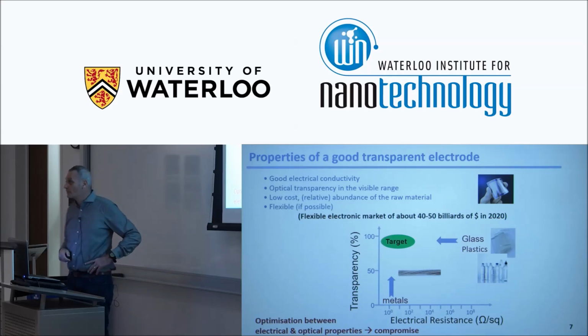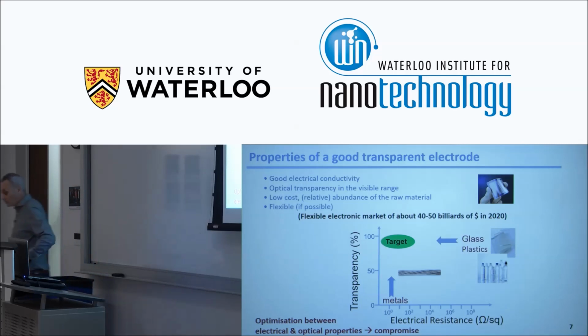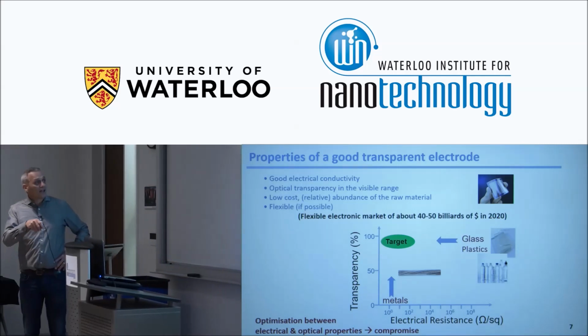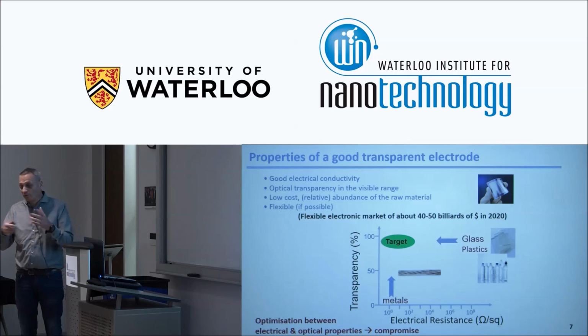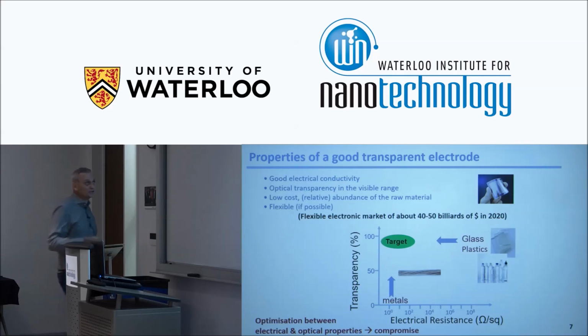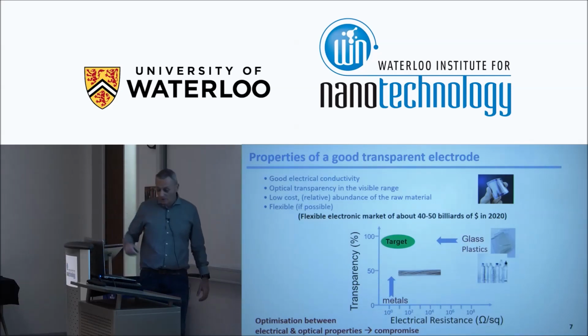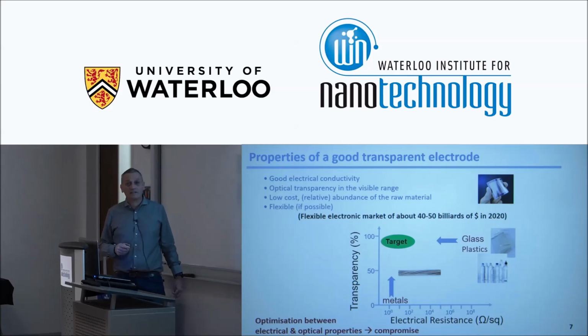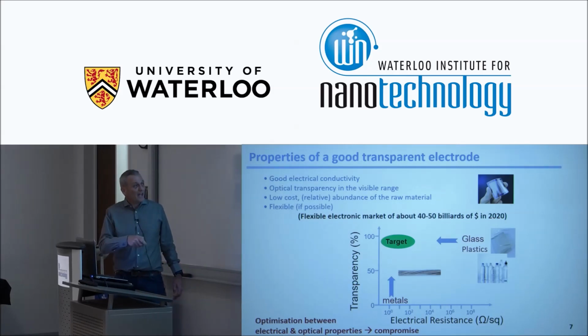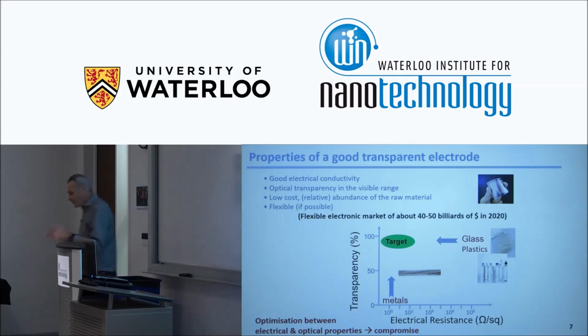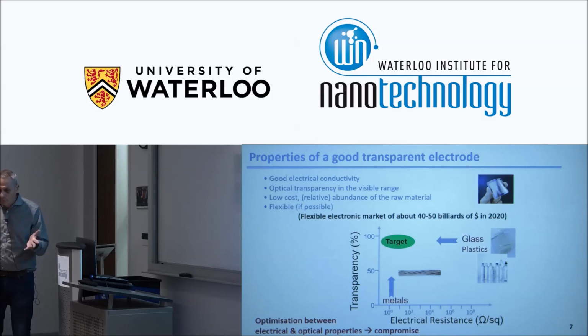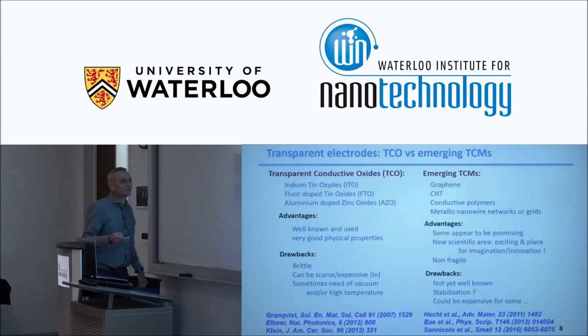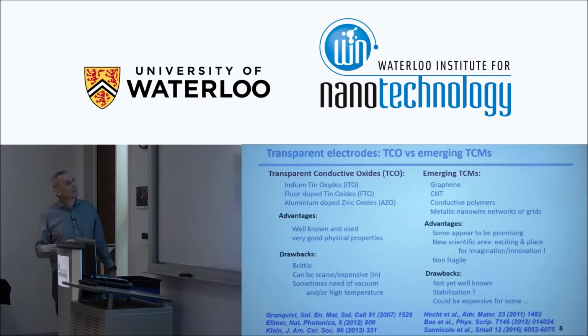Another way is to start with metals. They are very conductive, but they are totally opaque if they are thick enough. And the way we can work is with a spatial distribution of metallic materials in order, again, to reach the target. That's the case of a metallic grid, for example, or a metallic nanowire network. And this is, again, a compromise between electrical and optical properties. The more material we put on a glass substrate, for example, or a polymeric substrate, the more conductive the layer will be, but it will become less and less transparent. So it's a question of compromise.